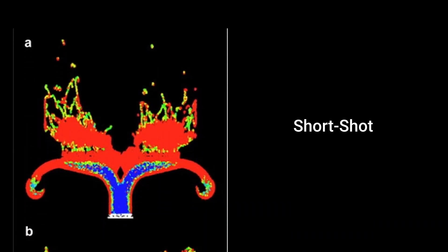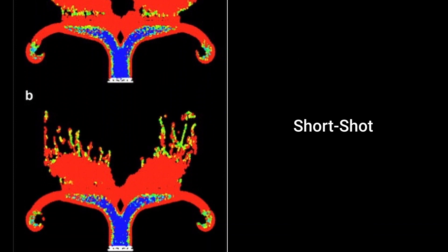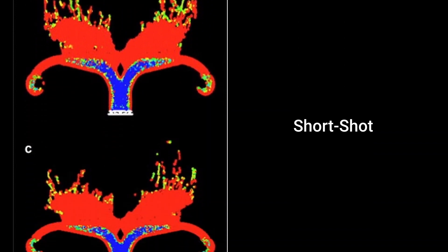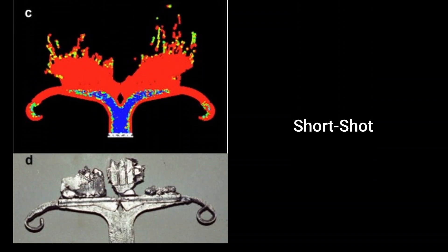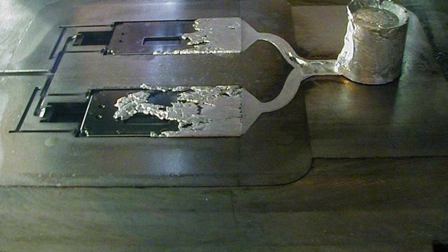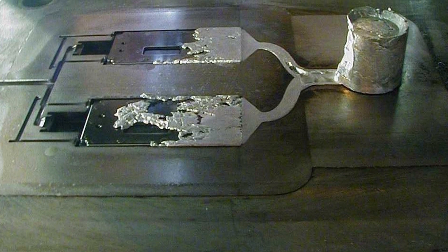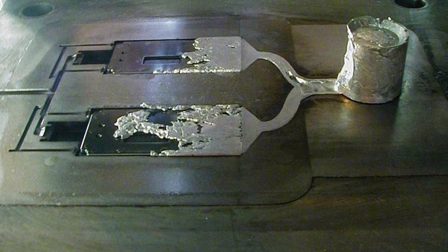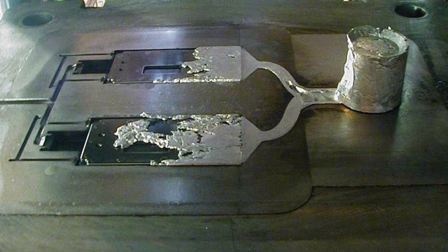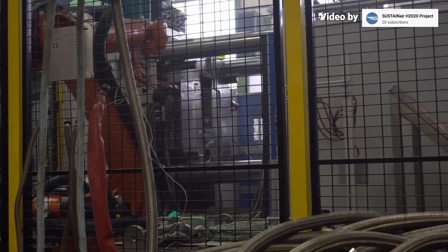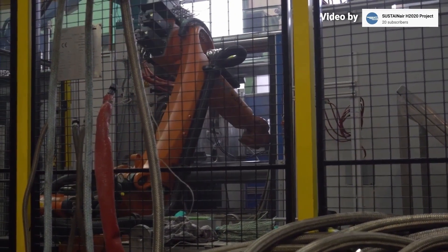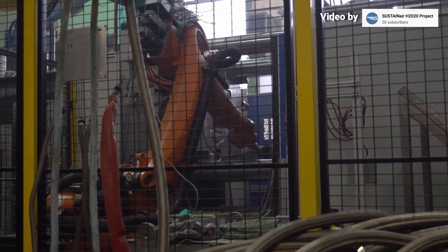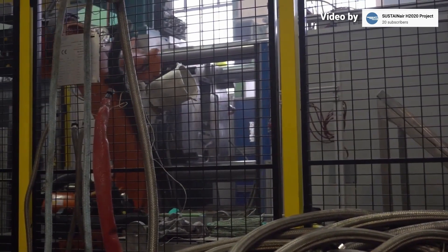The first type of porosity is called a short shot. Although it's technically not porosity, it is a real pain and it's made up of air, at least whilst it's still in the mould, but arguably it's the easiest to deal with. Short shots usually occur when there's not enough pressure or speed to get the aluminium out into the farthest reaches of the cavity before it freezes off. One solution is to play around with the injection parameters and maybe even add some additional overflows and venting.